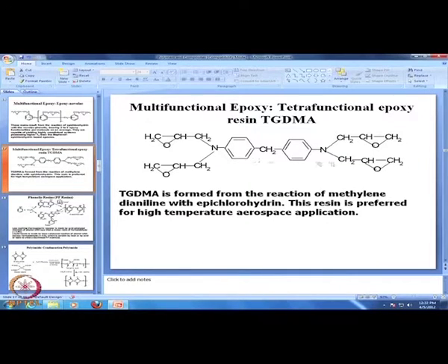So, when this is polymerized, that leads to huge cross link density, and it contains this CH2 linkage, CH linkage, all these things, as well as CH2 linkage and aromatic linkage and oxygen. So, this gives a combination of very strong and tough as well as thermally stable composite.